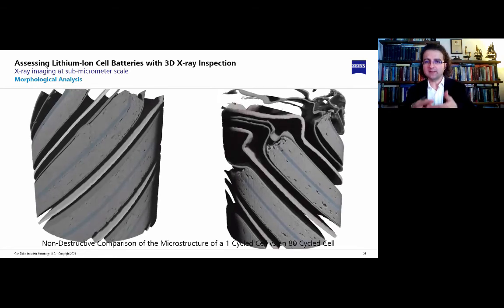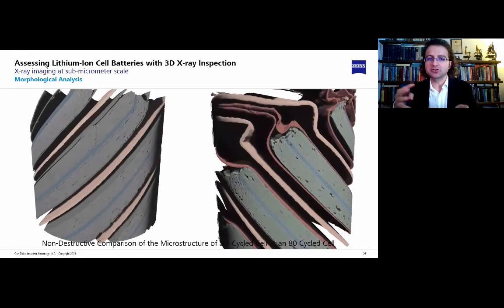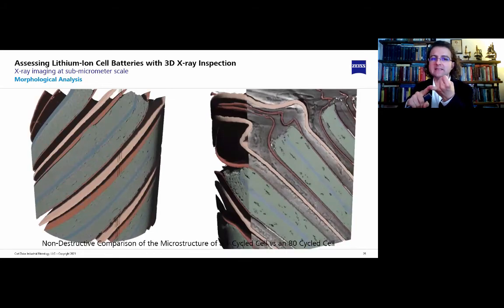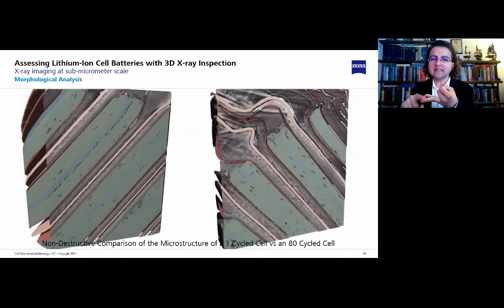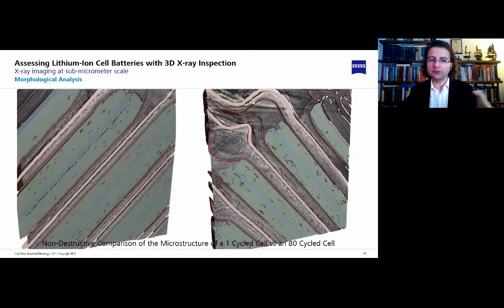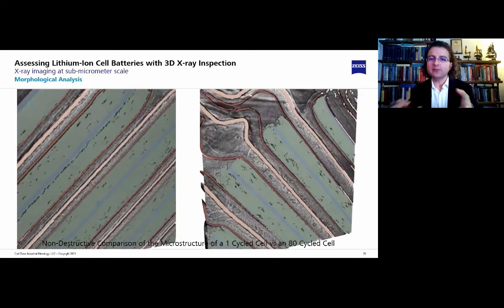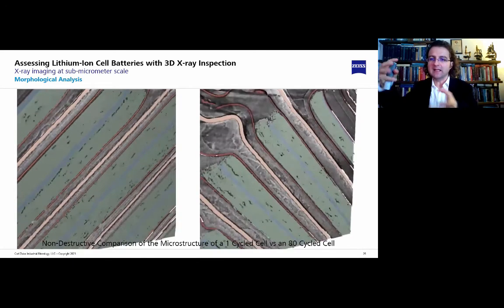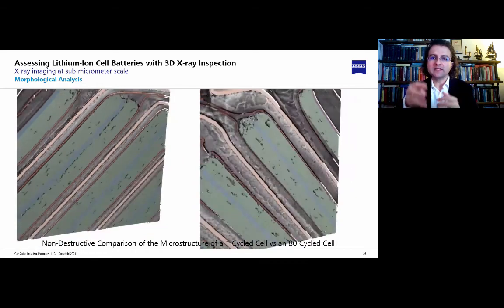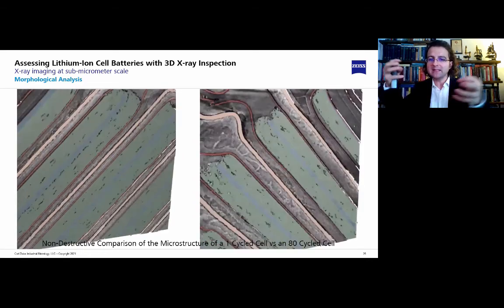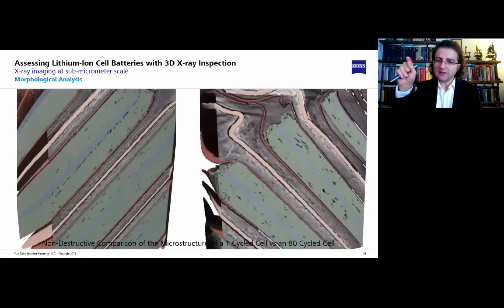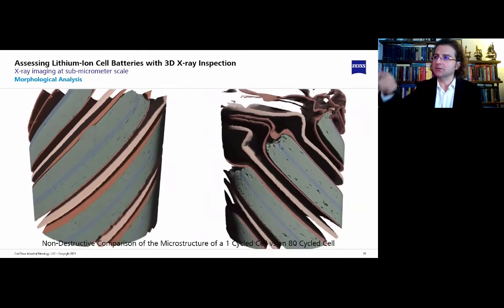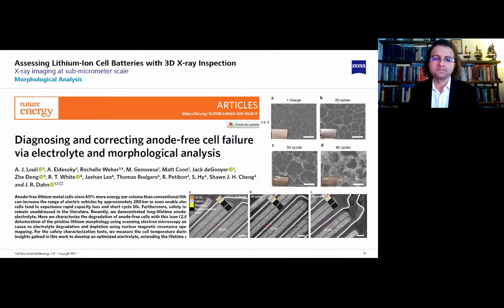This video shows a non-destructive comparison of the microstructure of a one-cycle charge versus 80 cycles, where you can easily see morphological changes, mechanical deformation at the edges of the electrodes, stress formation, and some variations of the radial distance and separation of different interlayers in the battery, as you can see at the top.